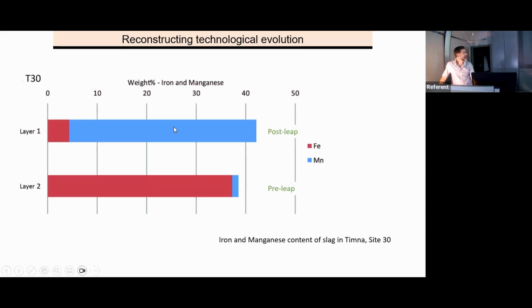In Timna, in the layer before the leap, the deeper layer on site 30, you see that the flux was iron. The slags are rich in iron, almost 40% iron, because they were using iron oxides as a flux. But then there was a major change, and in the upper layer they switched to a different flux, manganese oxides. So there is a major change in the use of flux in the south only. They learned from somewhere that manganese is a better flux than the local iron, and they started mining manganese oxides and added it to the smelt. Okay, I hope you are still with me.